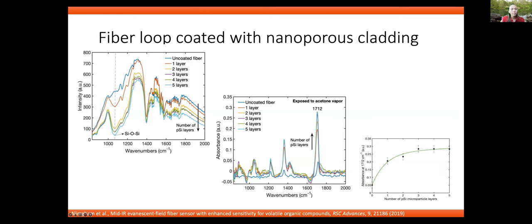So we also exposed those fiber probes, after we coated them with different numbers of layers, to acetone vapor. And we can see that the acetone vapor peak here, which is characteristic of acetone, increases as a function of number of layers. And if we plot the number of layers as a function of the peak intensity, we can see that going from zero to one layer, it significantly increased our intensity. However, if you add more and more, the effect decreases.